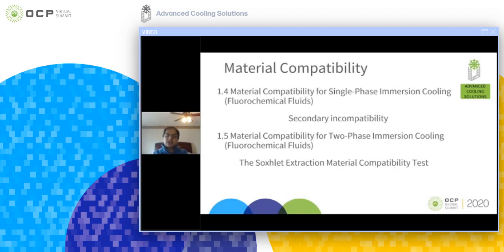We have some ASTM standard test methods like D471 or D2210, which exist in the market for transformer oils, but with the right modifications, we can utilize them for immersion cooling with hydrocarbon oils. The first test is general material compatibility, where you are certifying the server under operation. First you do visual inspection, you check for the effects of contaminants, pools of oil, and you check thermal performance, and also do microscopic images by doing cross sections and that kind of test.